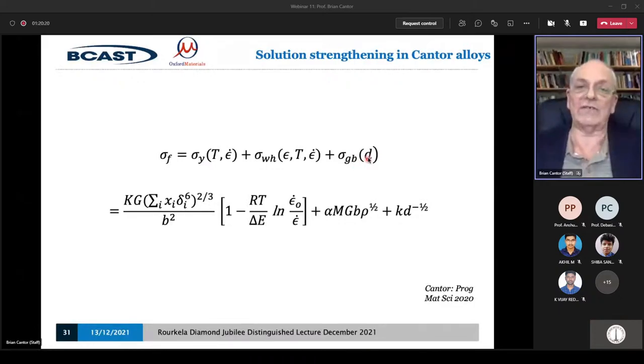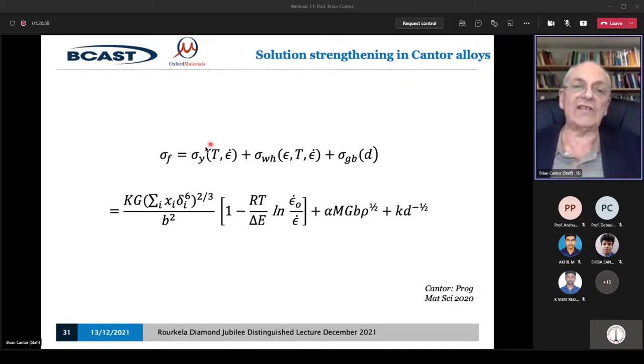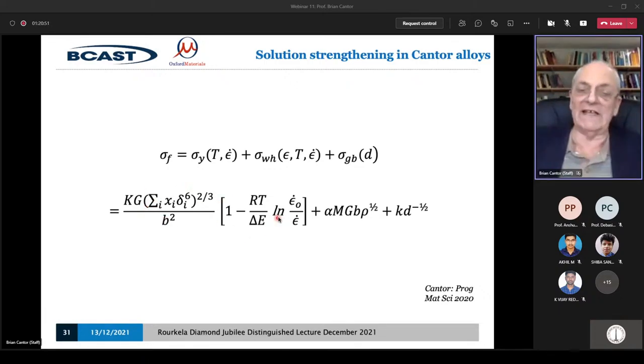They have lots of crystals in them. These two are exactly the same. It doesn't make any difference whether you're dealing with a single component material like pure gold or pure copper or the Cantor alloy. They're what's called Taylor work hardening and Hall-Petch grain boundary strengthening. Those are technical terms. Don't worry about them. It's this term, the basic difficulty of moving the dislocations through the lattice. And this is the theory. The theory tells you this is what should happen if every atom acts as a sort of strain barrier. Don't worry about the details of this. Let's look at the output.